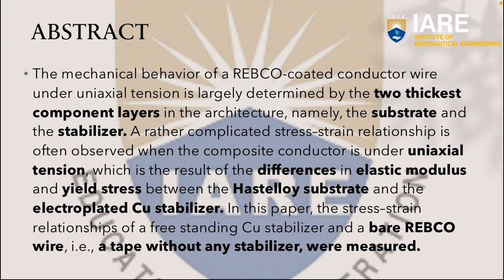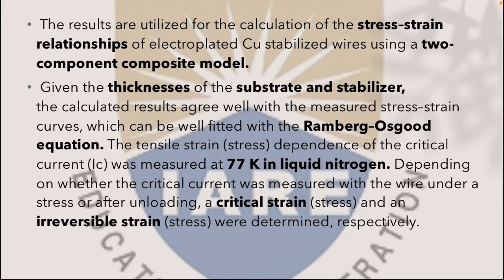In this presentation, the stress-strain relationship of a free-standing Cu stabilizer and a bare REBCO wire, that is a tape without any stabilization, was measured. The results are utilized for the calculation of the stress-strain relationship of the electroplated copper stabilized wire using a two-component composite model. Given the thickness of the substrate and stabilizer, the calculated results agree well with the measured stress-strain curves, which can be well fitted with the Ramberg-Osgood equation.